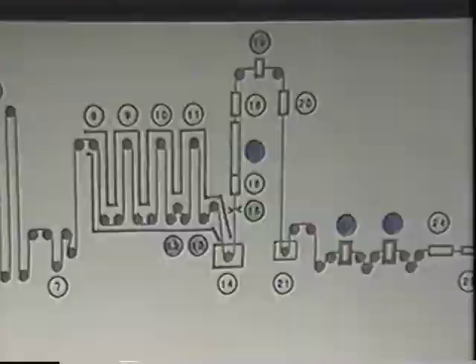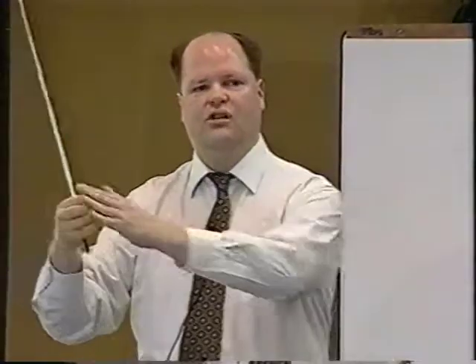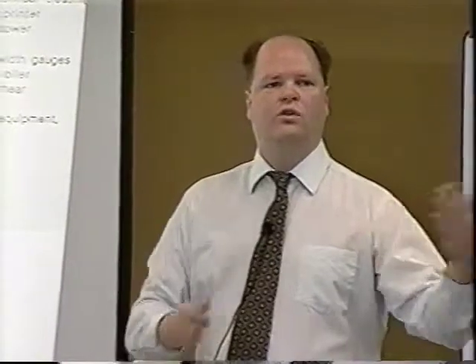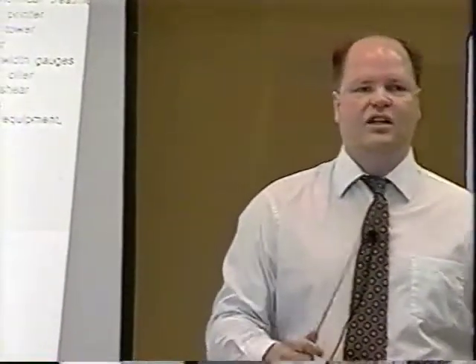So there is a delay there, but it's a continuous line, a continuous strip. It shouldn't be very much change. I mean, across one coil, once it hits 60 grams at the start of it, it shouldn't really change very much to the end of it. There's no real reason to. The problem arises when you're switching coating weight aims from one order to another. If you're going from 60 to 90 or 90 to 60, then it has to make a pretty quick change.